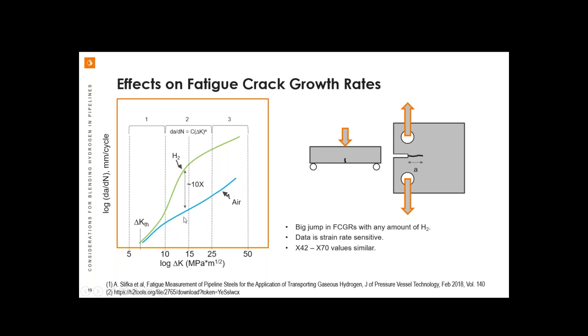But what does matter is if you start to add hydrogen, and it could be any amount of hydrogen, maybe just a few psi. If you get above a certain stress intensity level, that growth rate in millimeters per cycle can go 10 times higher. And then it will stay that way for the remainder. So this is definitely an item of concern. If we can have a big jump in data that happens with a small amount of hydrogen addition, and that seems to be more important than the actual grade of the alloy.